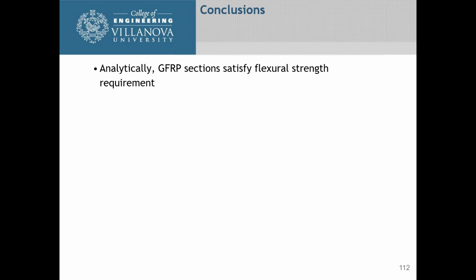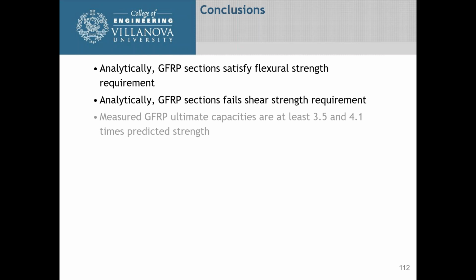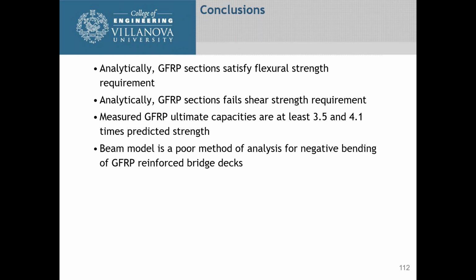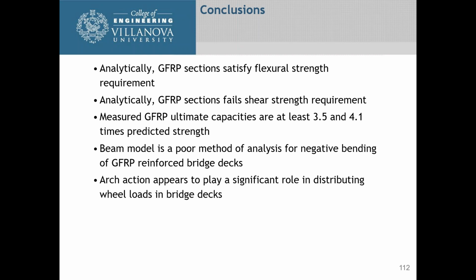Analytically, the GFRP sections satisfy flexural strength requirements, but the GFRP fails the shear strength requirement if you look at it analytically. But we realized from our measurements that the capacities were 3 to 4 times what we predicted based on the formulas. This leads us to believe that more testing has to be done on the formulas for the shear capacity because you're getting more capacity than is actually predicted. And one of the other things that we concluded was that the beam model is a poor method of analysis for negative bending on GFRP reinforced bridge decks. Arching action appears to play a significant role in distributing the wheel loads through a deck.